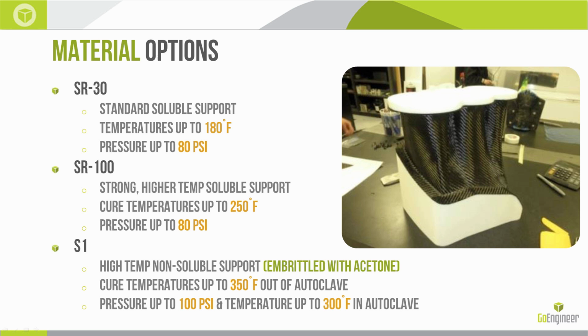The last option here, I'm kind of cheating a little bit, because this isn't soluble, but we can still create hollow composites from it. So this is a high temp, non-soluble support. We use the S1 material with our Ultem materials. It's not soluble, but we can embrittle it with acetone. So instead of dunking this in our wash station or our ultrasonic bath, we would actually pour acetone or paint acetone onto the support material, let it soften, and then we'd break it out mechanically, pliers and whatnot. The benefit of doing this, it's extra work to get the core out, but we can have cure temperatures up to 350 degrees at ambient pressures. Or we can go up to 300 degrees Fahrenheit and 100 psi in an autoclave.